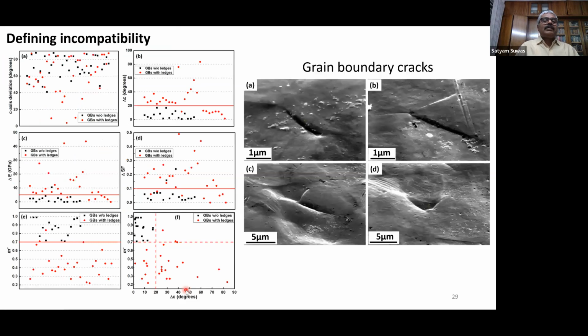We also examined the compatibility of all the grain boundaries with respect to C-axis deviation, grain boundaries with ledges and without ledges, all these things. And here is the result. We could see that the scatter is quite substantial in this case. The C-axis deviation here is in degrees. The black dots indicate grain boundaries without ledges, and the red dots indicate grain boundaries with ledges. If we consider delta E, the change in elastic modulus, we could see that there is more scatter for the grains which have exhibited ledges at their boundaries compared to the ones which have shown no ledges.